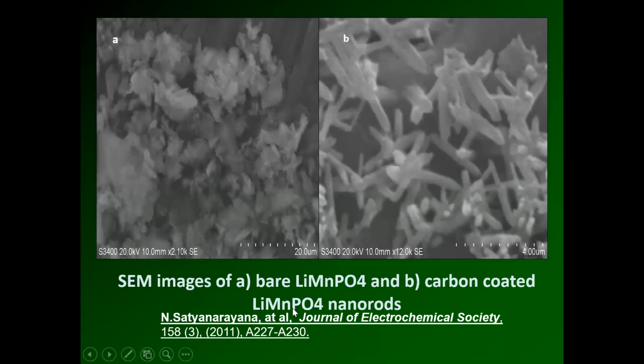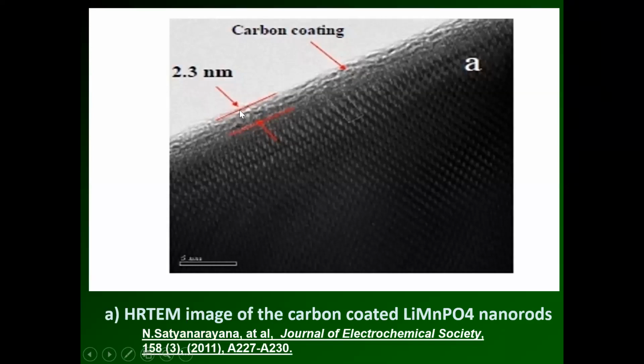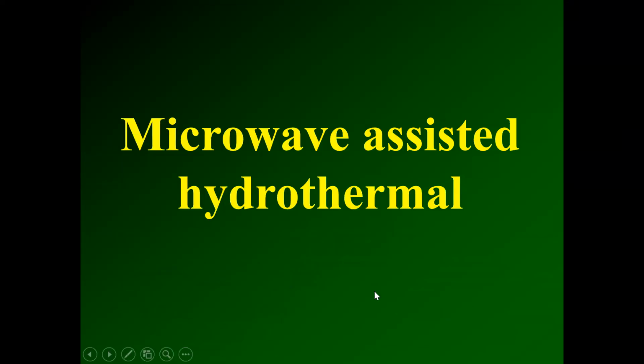Then similarly, we have developed nanorods of lithium manganese phosphate. This is a very good material for lithium battery applications. You can see nanofibers, nanorods, and carbon-coated nanorods. The carbon coating is 2.3, as you can see from the elemental analysis. This is on lithium manganese phosphate, and it is published in the Journal of Electrochemical Society. So that is the combustion and polyol method.